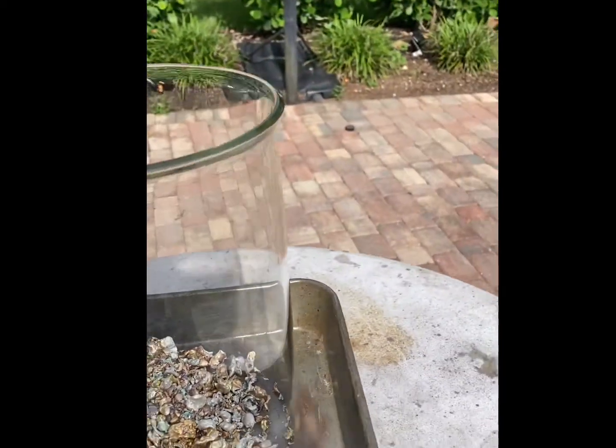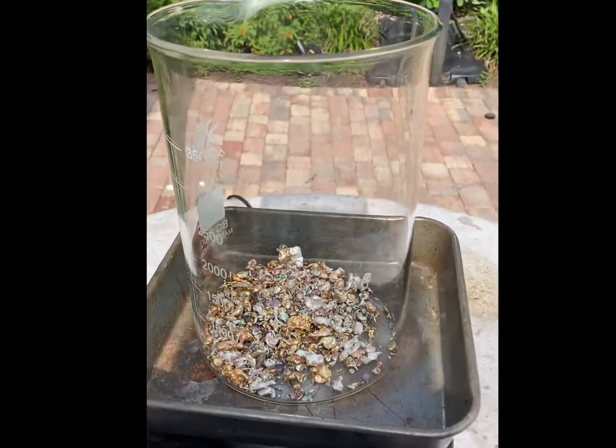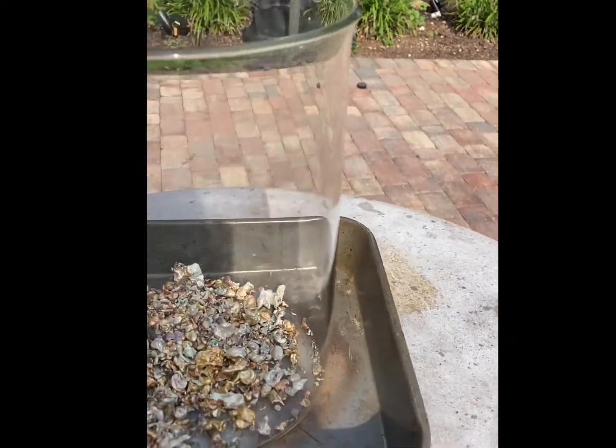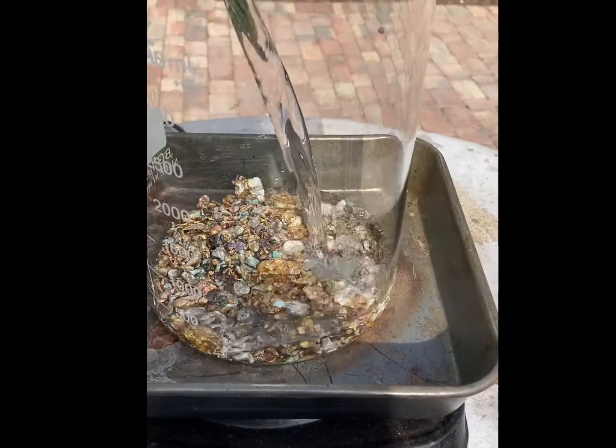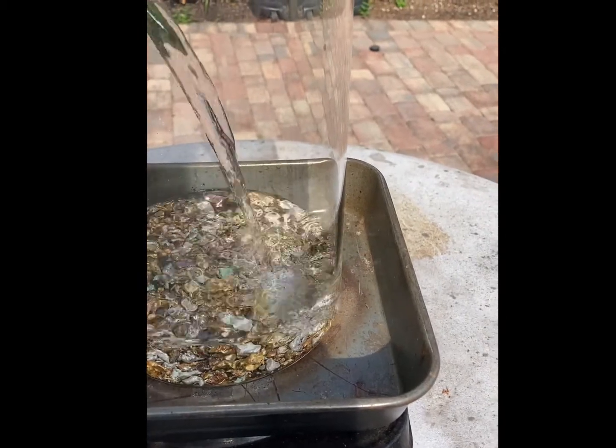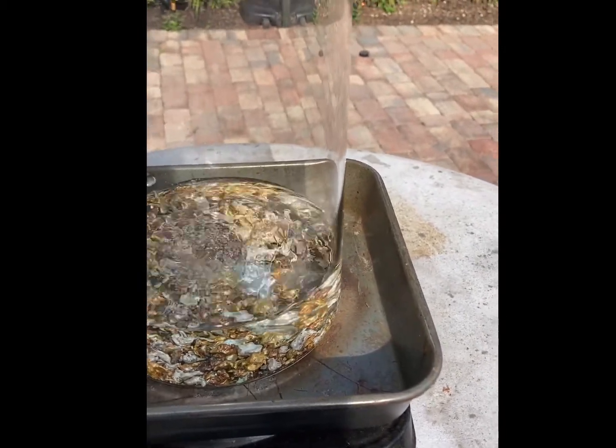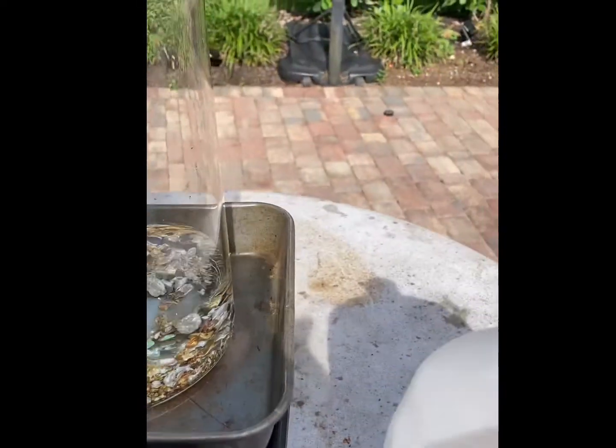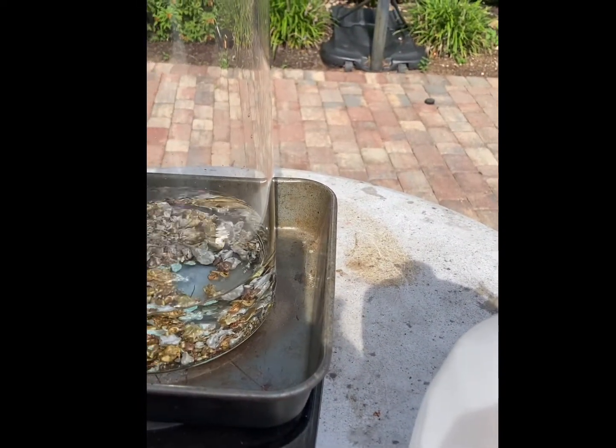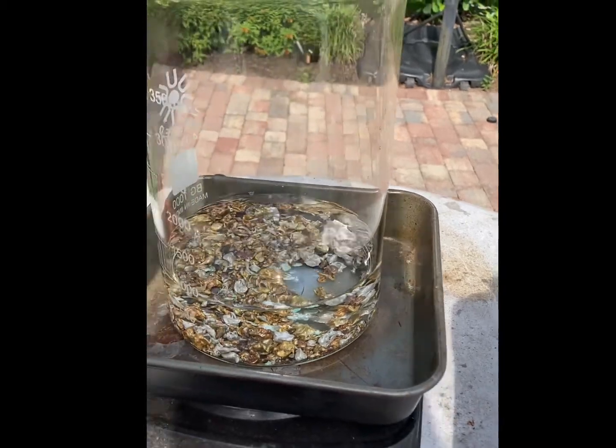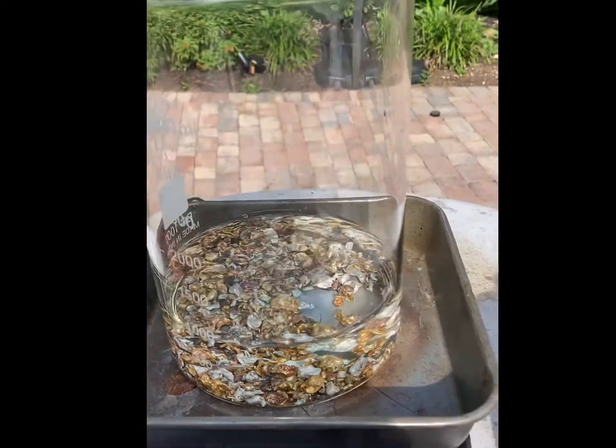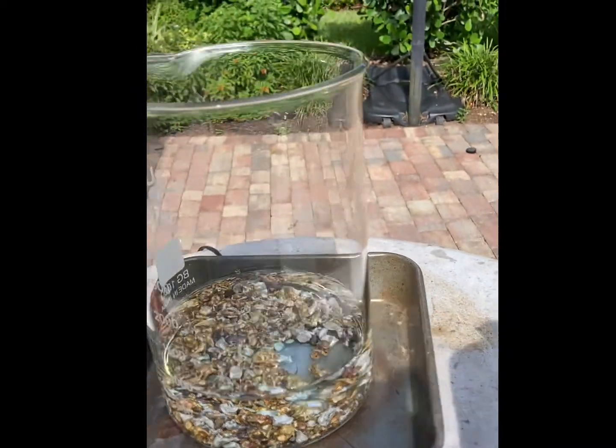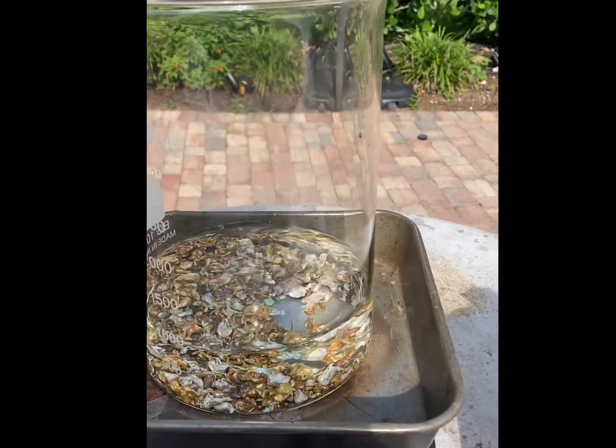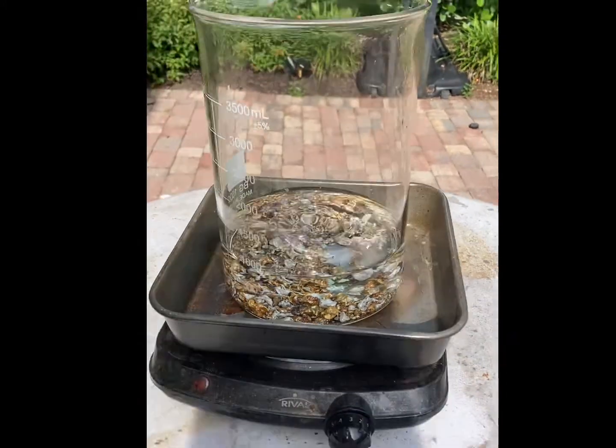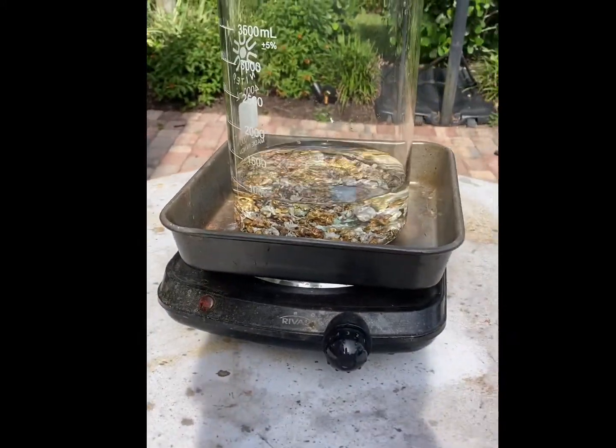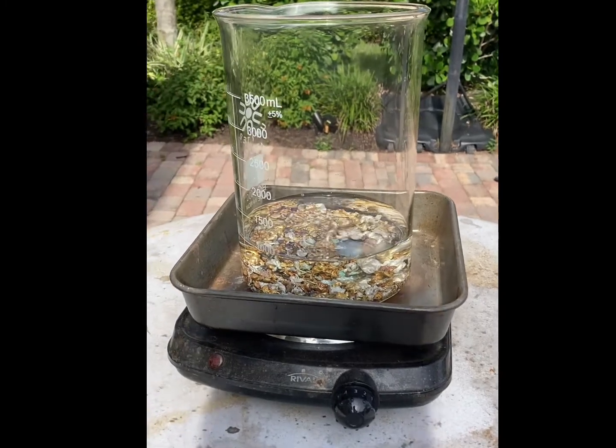Start off with again 500 grams of silver, and I start with 1,000 milliliters of distilled water. I like to bring it up to temperature before I put the nitric acid in. I just feel like I can control a runaway reaction better if it's already hot. I don't have to watch it so closely. So I'll let that heat up for a minute, and then we'll put in 100 milliliters of distilled nitric acid.